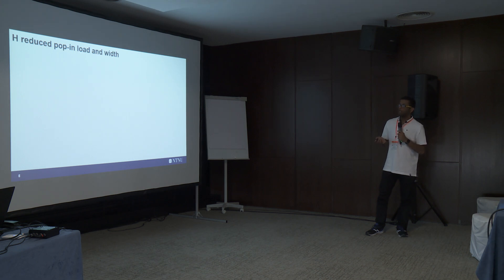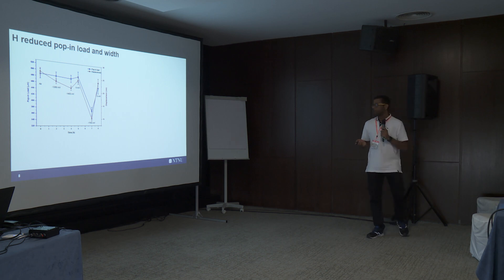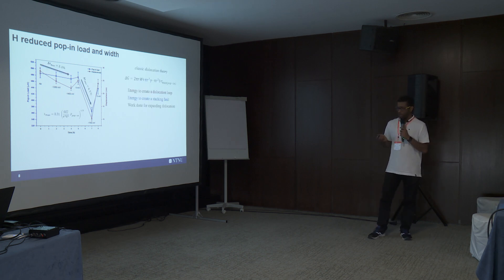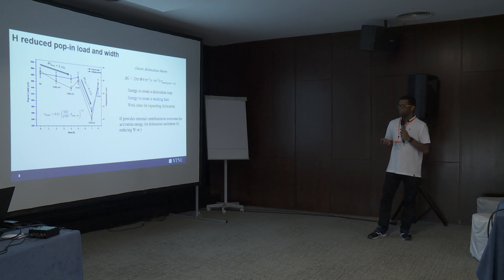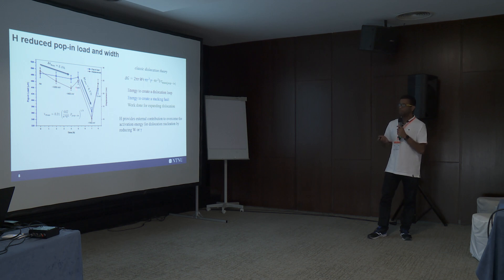There are three key points to discuss. First, the hydrogen-reduced pop-in load can be explained by defect theory. According to classical dislocation nucleation concepts, the free energy required to nucleate a dislocation can be expressed with this equation. Under the presence of hydrogen, the first two terms — the energy required to create a dislocation loop and the stacking fault energy — are reduced. In other words, hydrogen reduces the activation energy required for dislocation loop formation, so the load required to initiate plasticity in the hydrogen-charged sample is reduced.